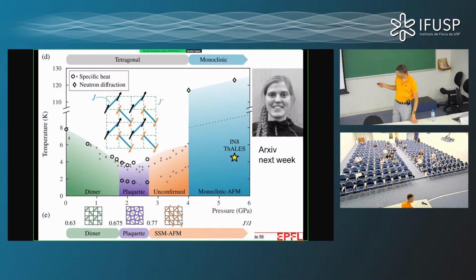and a good guess for this phase would be that while we're still in the Shastry-Sutherland model, so while we still have the square lattice tetragonal crystal structure symmetry, we actually do get an antiferromagnetically ordered state, so that this would be an antiferromagnet, but that has not been confirmed. Right? So all we know is that there's some phase here, and we have not been able to confirm what it is. And we have also tried to measure the excitations here.